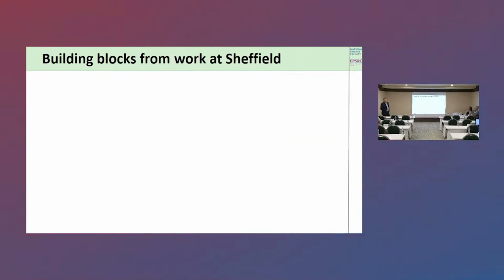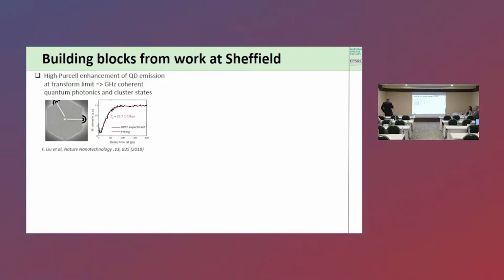So there's been a lot of work done at Sheffield as the scientific building blocks for making the kind of quantum circuits that I've just indicated there. And there's a couple of examples of things that have come out of that work. All this work is basically being done on gallium arsenide based quantum dots. So in particular, if you include your quantum dot inside a photonic crystal structure or cavity, you can get a high Purcell enhancement, and this then means you can shorten the lifetime down to, in this case, about 23 picoseconds. So that gives us the opportunity to do essentially gigahertz coherent quantum photonics, including the possibility of making cluster states.